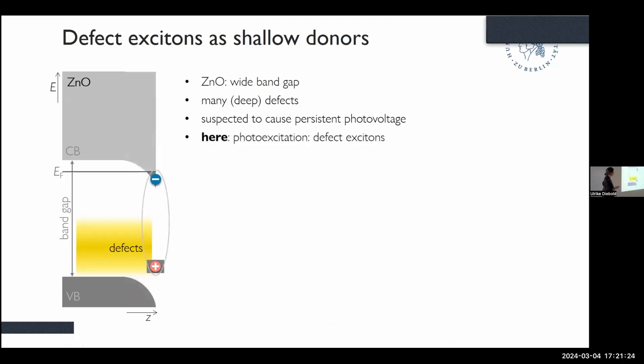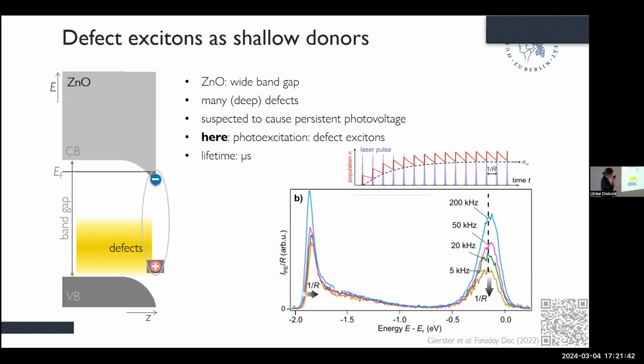So what I will show you here is that we photoexcite the system and we create defect excitons, and that we can play with the properties of the system by changing the density of these defect excitons. As a start, I've brought here a photoelectron spectra. So it's photoelectron intensity as a function of energy. Zero is always Fermi energy. And you see that here is a maximum just below the Fermi energy, so normally occupied states. And the intensity of this feature changes as we change the repetition rate of our laser system. So for the ones who have not been working with ultra-fast pulsed lasers, we work at kilohertz rates.